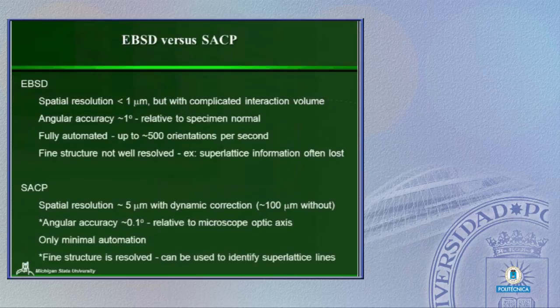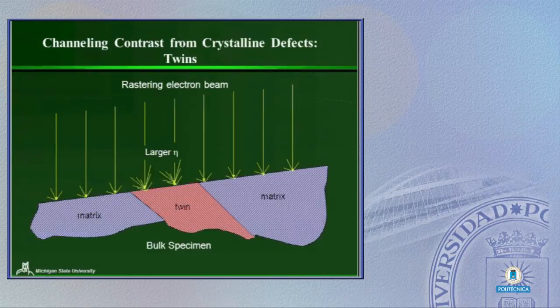With selective area channeling pattern, about the best we can do is maybe about 5 microns. So the spatial resolution is not nearly as good. If we don't have dynamic correction, it's going to be even worse, about 100 microns, which really starts limiting this approach. But the angular accuracy relative to the optic axis is quite high. It's about 1/10 of a degree, maybe a little bit better. Only minimum automation, which my students don't like because it makes them work hard. Okay? And we do get fine structure resolved, which I'll give an example of here, how that can be very useful for us.